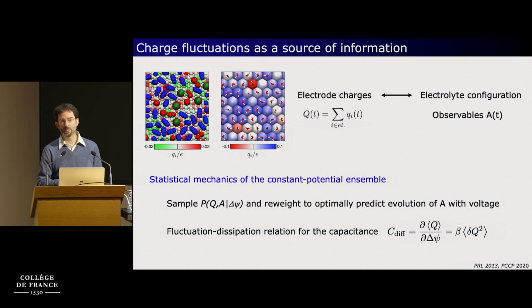So what I would like to emphasize today is rather the fact that you can learn a lot by analyzing the charge distribution inside the electrode. And as you will see, many of the properties of the interface are related to this charge on the electrode atom. So here you have two snapshots from two different simulations. One is an interface between a graphite electrode and an organic electrolyte with these butyl methyl imidazolium cations, hexafluorophosphate anion, and in that case acetonitrile solvent molecules. And here you have water on a platinum electrode.